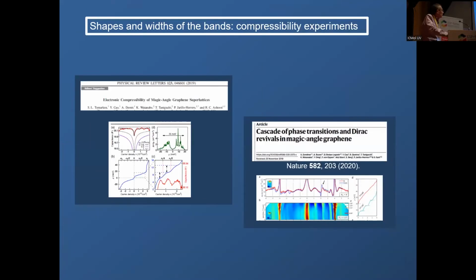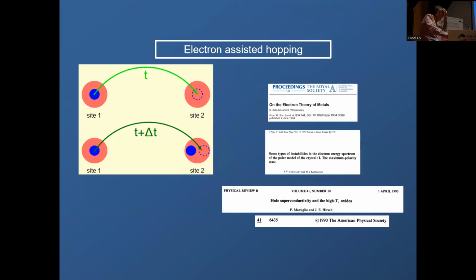And these are more experiments, compressibility experiments, which also allow you to measure the width of the band. And what that means is quite interesting. That means that there is an interaction in twisted bilayer graphene which you don't find in other systems. If the band shape changes as you change the number of carriers, that means that you're somehow changing the hoppings between the Wannier orbitals associated to these bands, and that's called electron-assisted hopping. That was a topic widely studied by Jorge Hirsch way back in connection with the cuprates, and he suggested correctly that this points to superconductivity. It's an interaction which cannot lead to charge density waves or magnetism or anything like that, so the only other instability left is precisely superconductivity.